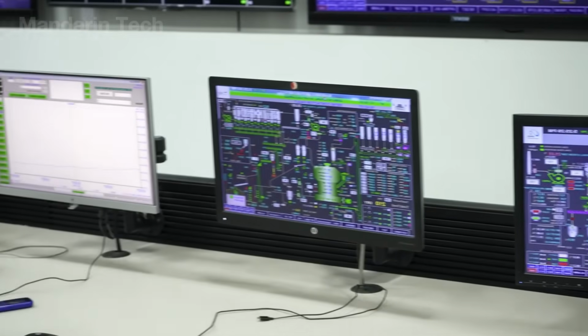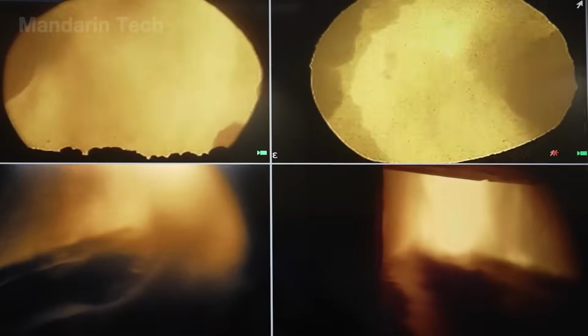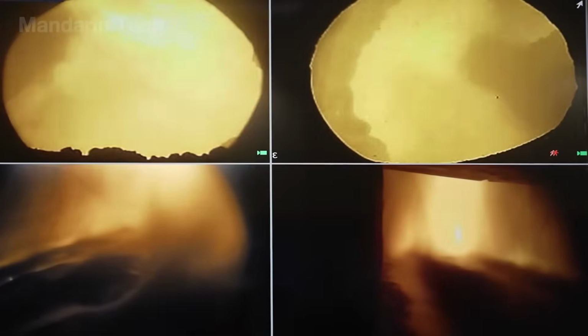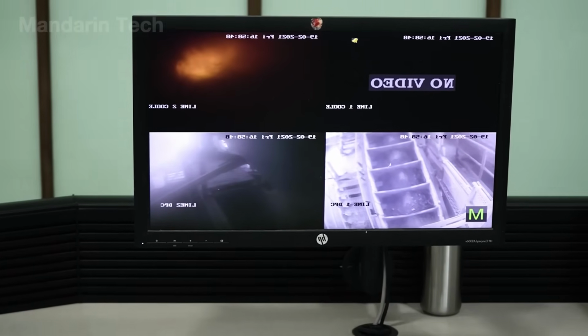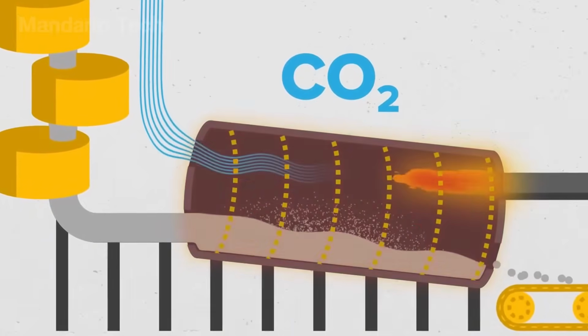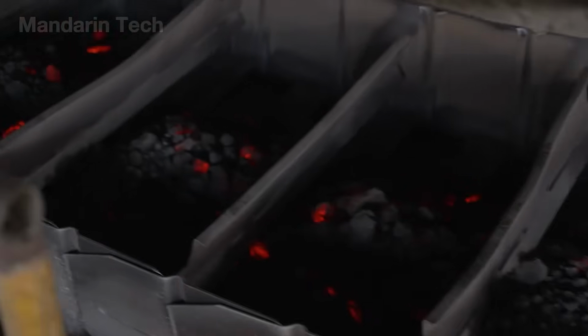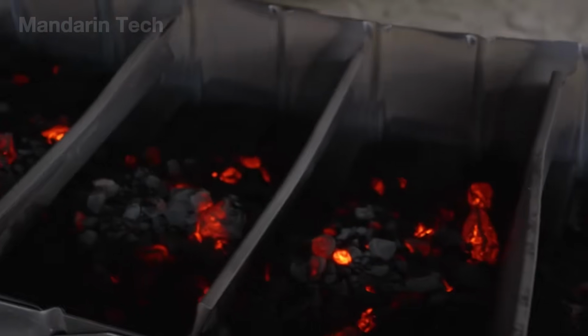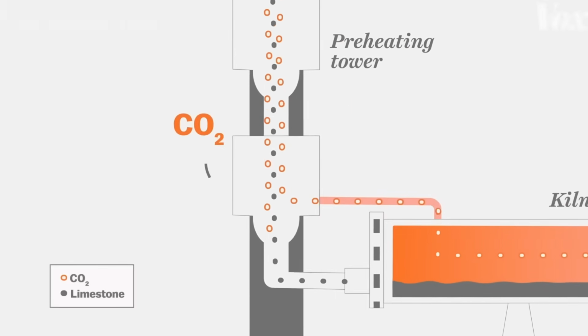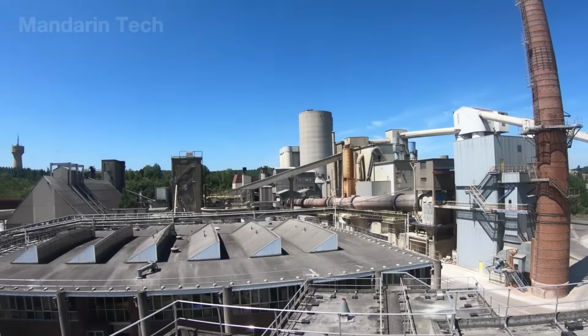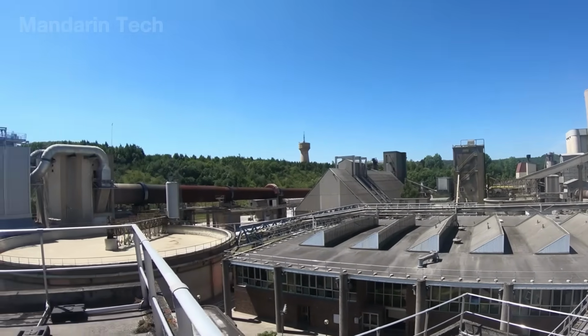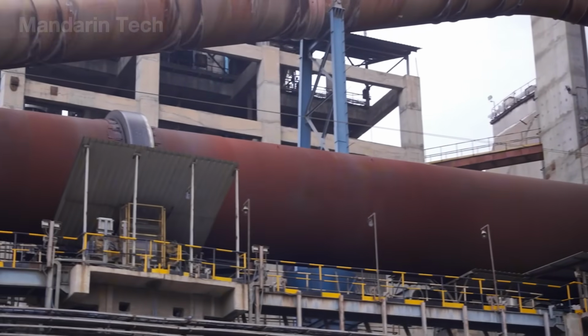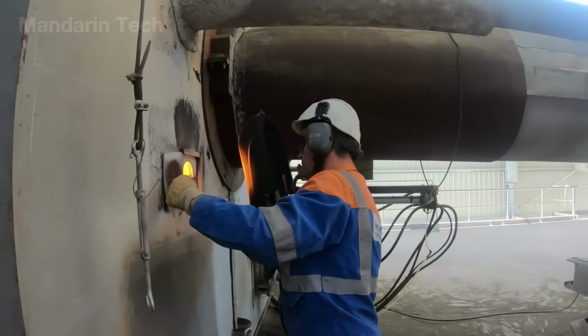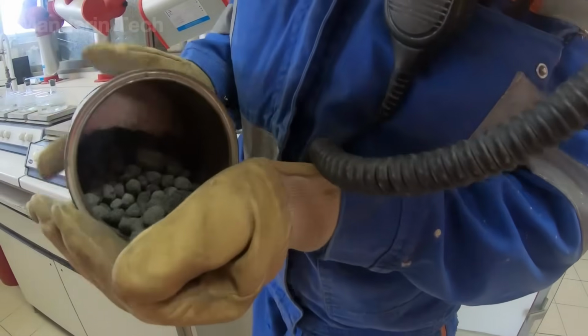To keep conditions stable, the control system constantly monitors kiln speed, fuel flow, and gas pressure using heat sensors and infrared cameras. The burners inject fuel in a swirling pattern, creating a long, penetrating flame that transfers heat deep into the material bed. Hot gases from the decomposition reaction are drawn out at the kiln inlet, carrying most of the CO2, while excess heat is recovered and sent back to the preheater. Along the kiln, the material gradually fuses into glowing red clinker nodules, rolling steadily along the kiln axis in the constant roar of fire and steel.